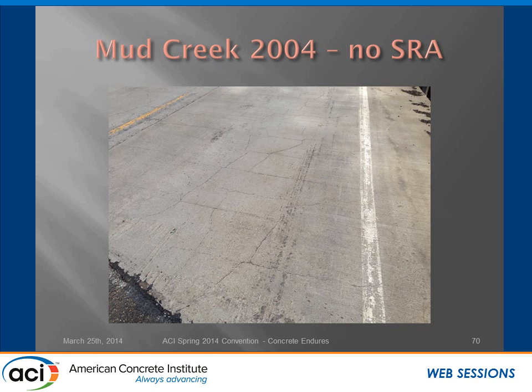And that's the case with this one. We didn't have a lot of funds in contingency when we realized that the deck was in serious shape that would not really support putting the expensive polyester overlay on. So we put a piggyback deck on. It's a pretty common Band-Aid that we do, where you dowel in, put a mat of rebar, and throw some concrete on it. In this case, we didn't have a lot of money, so we didn't have a lot of time to spend waiting for water cure.